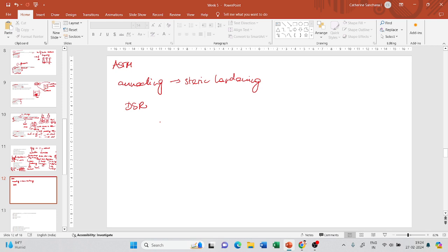So they also say that even after pouring it in silicone molds, since the volume is very less, since the mass is very less, how much volume or what is the size of the sample in a DSR? It is 8 mm diameter, 2 mm height, or 25 mm diameter and 1 mm height, right? So in that case, the sample is very small. So you should not be testing the sample beyond 4 hours.